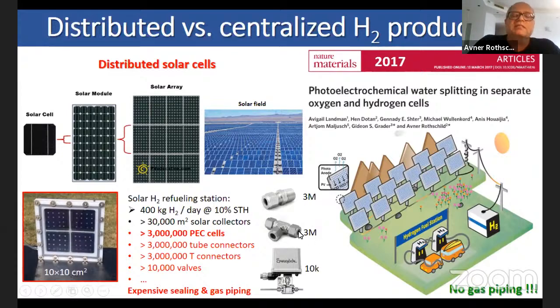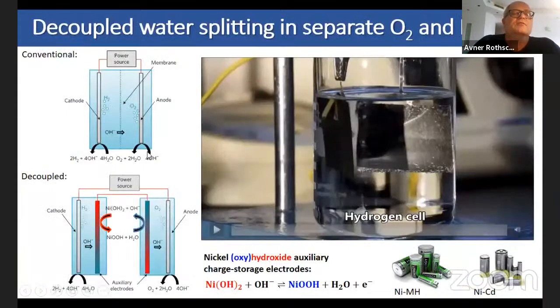So just the gas piping system gives you a ridiculous cost. So we thought out an idea how we can eliminate this gas piping system. Based on the idea that our hematite devices, the photoelectrochemical cell, generate only oxygen. The hydrogen is produced at the counter electrode. And if we can find a way to move away these counter electrodes and concentrate them, let's say at the edge of the field, then basically we can eliminate all this gas piping issue. And eventually we find a solution how to do this.